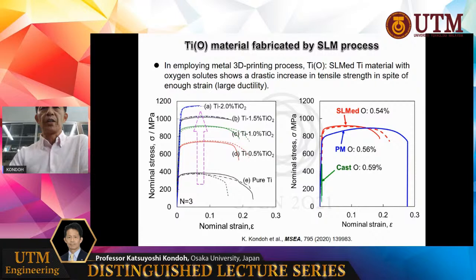But anyway, this data shows that the 3D printing process, in particular the SLM process, has a large possibility to improve the mechanical properties of titanium materials using ubiquitous elements like oxygen or nitrogen. Regarding the oxygen addition materials, my student, Ms. Ichikawa, spent much time to improve the strengths and ductilities of these materials. I thank her for her very nice studies.